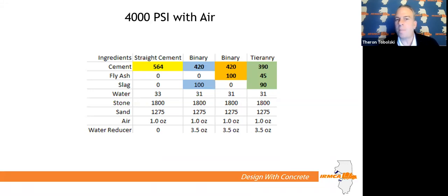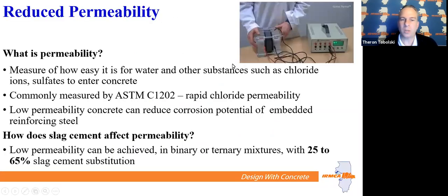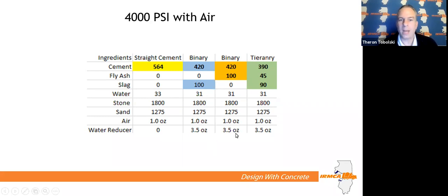And then what we call a binary mix. A binary means we have two cementitious materials. So this one actually has 420 cement and 100 slag. We drop down to 31 gallons of water. We actually add a water reducer at the bottom here, and we get above 4,000 PSI. You can also create a binary mix with 420 pounds of cement and 100 pounds of fly ash. Again, we add our water reducer and we're a 4,000 PSI mix.